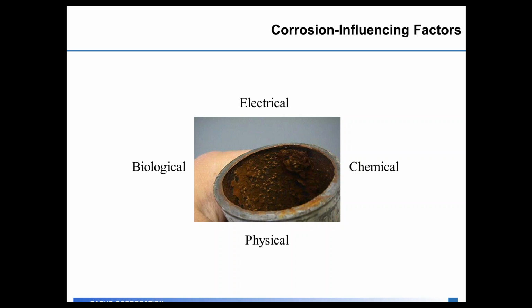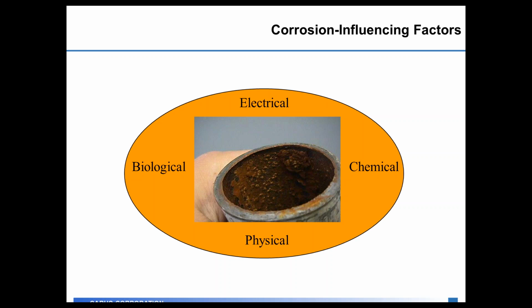And then finally, there's a biological portion to the distribution system. The reason that you maintain a chlorine or chloramine residual out in the distribution system is you want to keep those bacteria in control and not growing in the distribution system. If iron bacteria or sulfur bacteria start to grow in the distribution system, those can lead you to red water complaints in the case of iron bacteria, or hydrogen sulfide rotten egg odor in the case of sulfur bacteria. So now the water has picked up either a color or an off taste in the distribution system. It's those four factors all together that influence what type of corrosion you could have going on out in the distribution system.